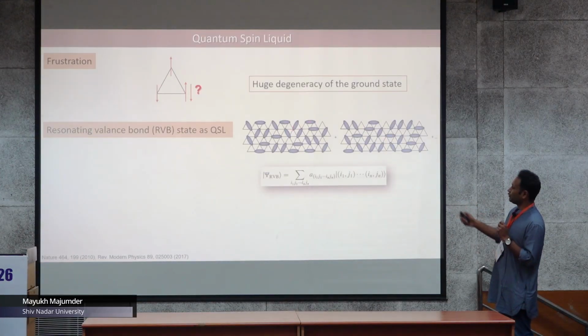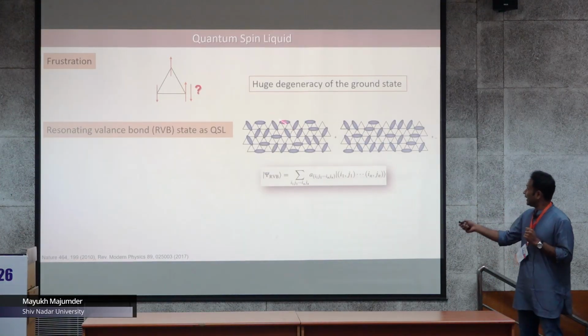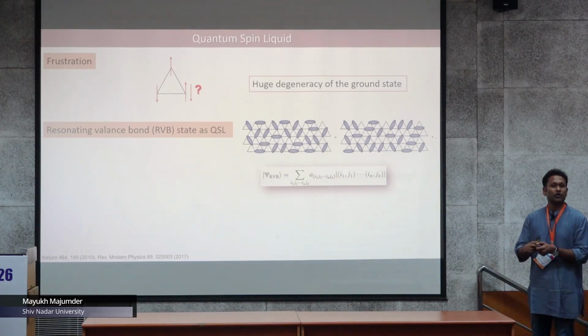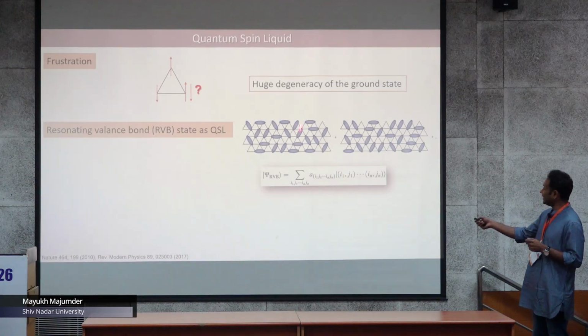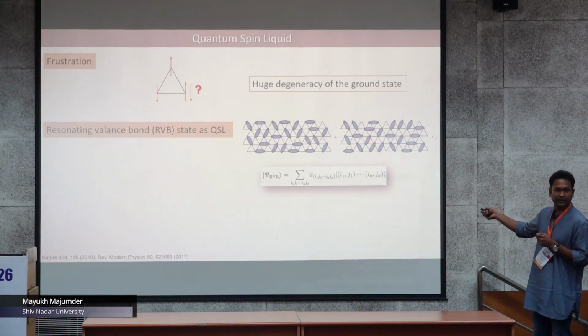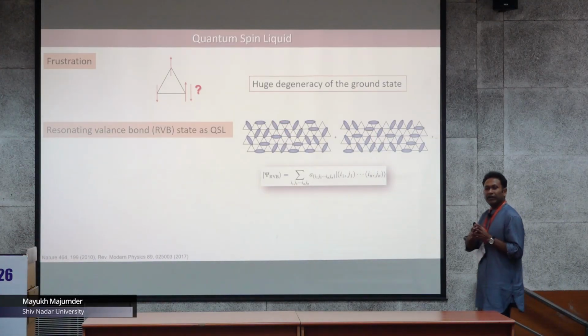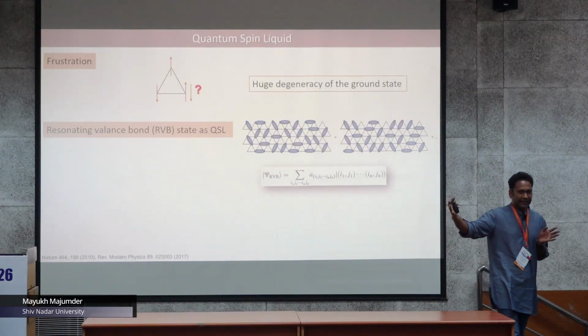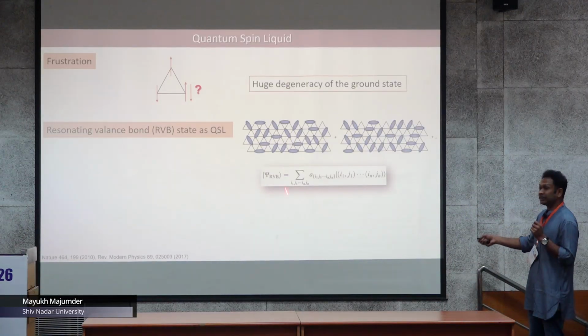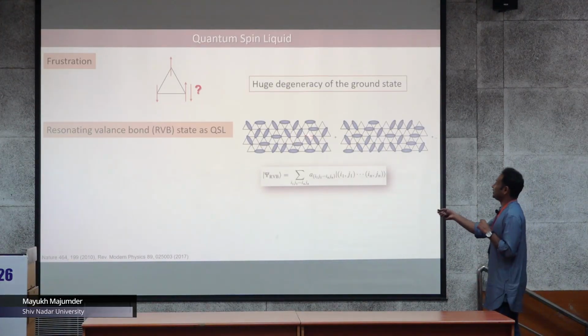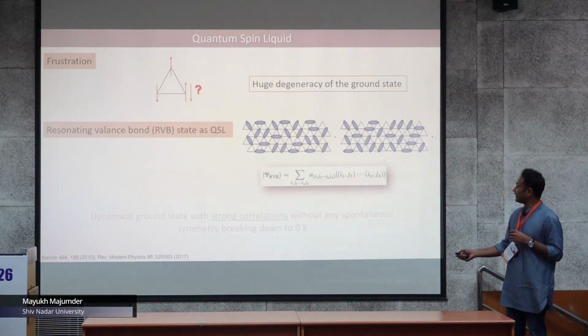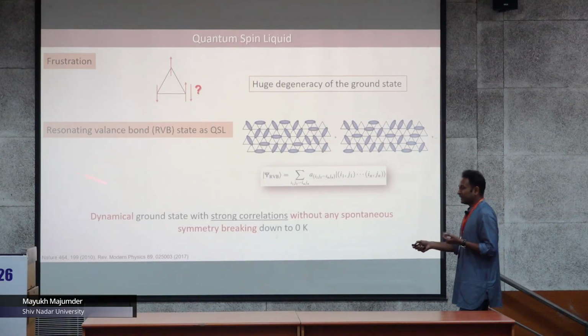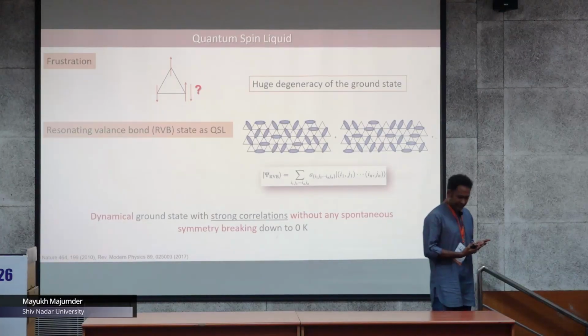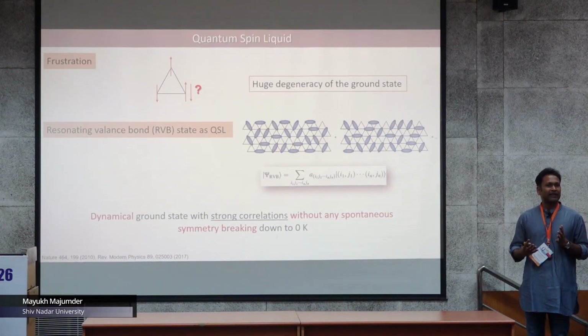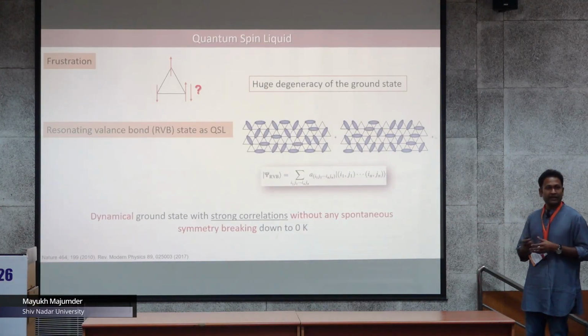So if you consider a triangular lattice, you can see that the nearest neighbors are forming some sort of singlet state, and this singlet covering throughout the lattice is different for this configuration and this configuration. Okay, so you can form a huge number of different coverings of the singlet and produce degenerate states, and the ground state is a unique state, which is the linear combination of all the states. Okay, and from there you can imagine that the ground state would be a dynamical state where there won't be any sort of spontaneous symmetry breaking even down to theoretically T equal to 0.